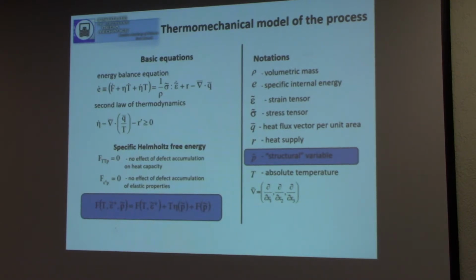It's a key question, and there are many books devoted to the thermodynamics of solids with defects. For example, there is no reference, but if you are following the way which was published by Razakis, and we propose that there is no effect of defect accumulation on the heat capacity, and no effect of defect accumulation on elastic properties, it's easy to show that we can write the energy as three parts.